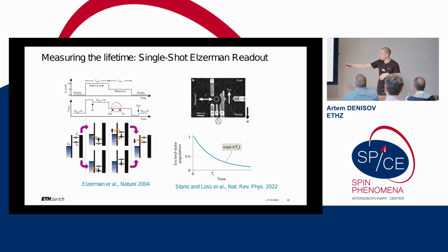So from an experimental perspective, the difference between these two cases is that you should have an additional bump in your sensor current shown here, which will mean that your dot at some point was empty, meaning that your electron in the beginning of the second pulse was in the excited state. And by measuring the probability of having this bump in your sensor signal as a function of waiting time after you load your electron, you can measure this exponential decay, and the exponential decay constant is going to be your lifetime. So, for how long can electrons survive in the excited state.